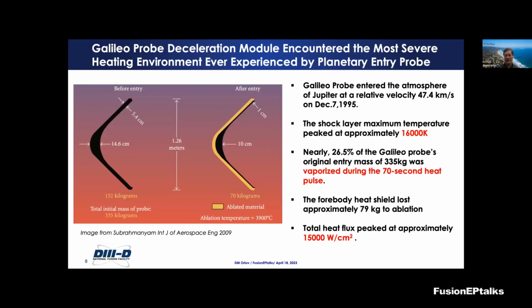Where was it? Yeah, I was saying that the re-entry was about 70 seconds. Our exposures were for two discharges of about 4 or 5 seconds each, so I think we collected about 9 seconds of high heat flux exposure of our samples. This is in the same ballpark, not exactly 70 seconds, but we could get the high heat flux on the target for 9 to 10 seconds, which is a lot under those conditions compared to any other experiments on Earth.